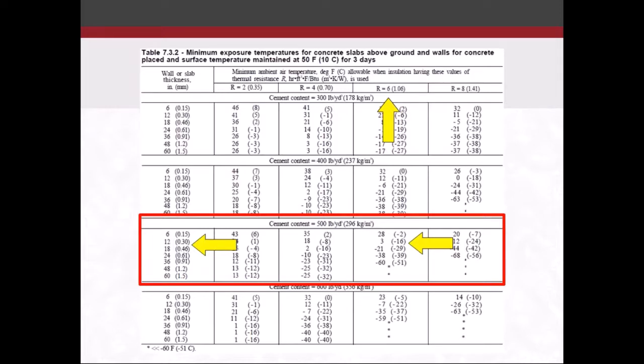So another table in 306 is this Table 7.3, and this is minimum exposure temperatures for concrete slabs above ground and walls for concrete placed and surface temperature maintained at 50 degrees for 3 days. So our protection period is 3 days, and we're maintaining 50 degrees for 3 days on walls and above ground slabs. We've got different portions of this table. Here on the left, this is our wall or slab thickness, anything from 6 inches to 60 inches. Then each set of columns corresponds to a concrete mix with 300 pounds of cement per cubic yard, this one's 400 pounds of cement, and this one here is 500 pounds of cement per cubic yard, and that's what I've highlighted here.